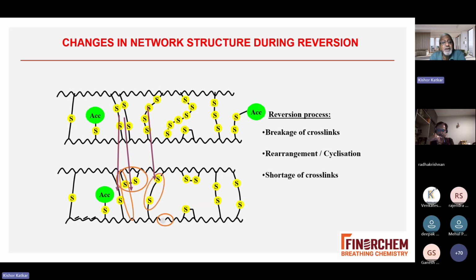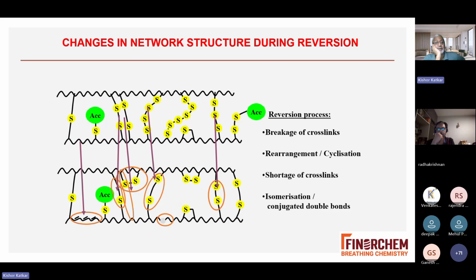Shortening of cross-linking: polysulfide linkages, which at high temperature in reversion will be substantially more, will give the di- or monosulfide. And then there are also conjugated double bonds in the main chain. So in a nutshell, what you observe is that the total cross-link density will come down, meaning your modulus will come down during reversion. And once the modulus and tensile come down, the performance of the product will come down. So in today's lecture, we will see how, with sulfur and accelerators, you can maintain or optimize the system and avoid reversion.